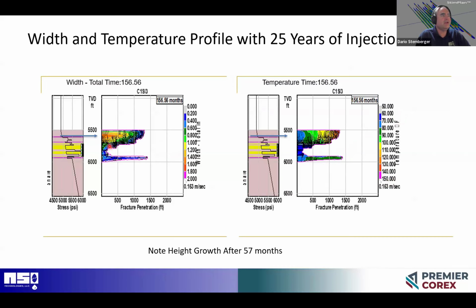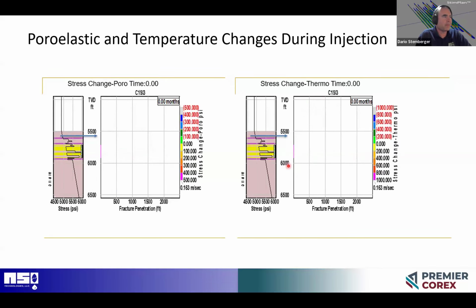And you'll see when this loops around again that up until about 57 months, we stay within the injection zone. And then when this hits about 57 months, we start breaking through the seal. We've got 2 of them here, and we've broken through, which means we've lost upper containment of the injection. We don't have any data above here, but we don't want to break through this seal, and that was the point of this simulation.